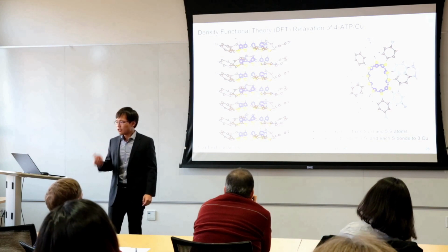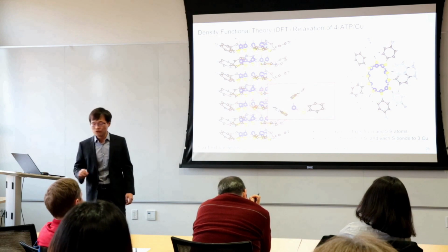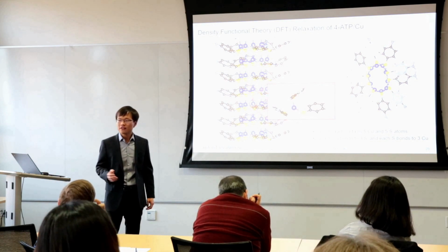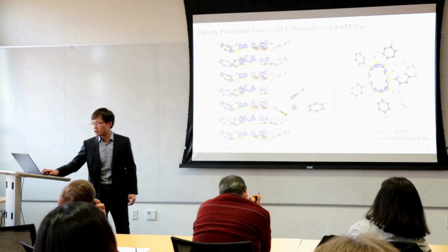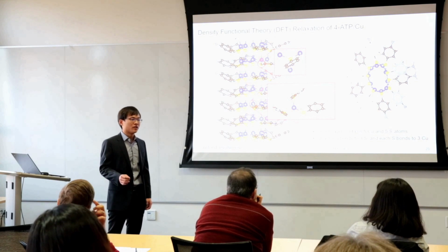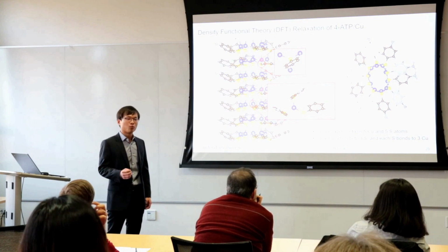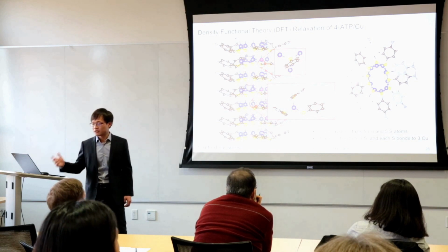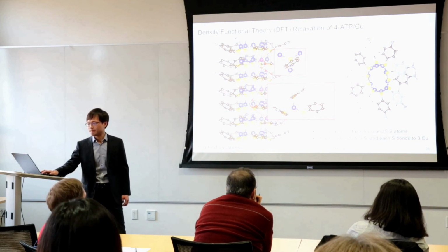Each copper atom binds to 3 sulfur atoms in a distorted trigonal planar geometry, and each sulfur atom, in addition to binding with its own aromatic ring, binds with 3 copper atoms in a distorted tetrahedral geometry.